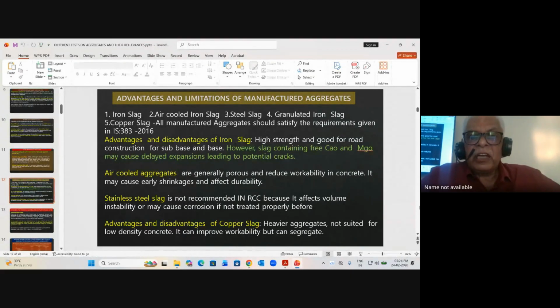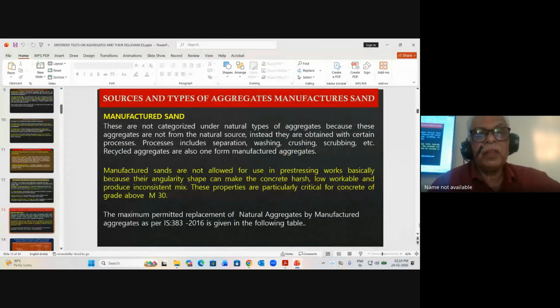Stainless steel slag is not recommended in RCC because it causes volume instability or may cause corrosion if not treated properly. Copper slag is a heavier slag, not suited for low density concrete. It can improve workability but can segregate concrete. These are the advantages and disadvantages of some of these. Manufactured sand.